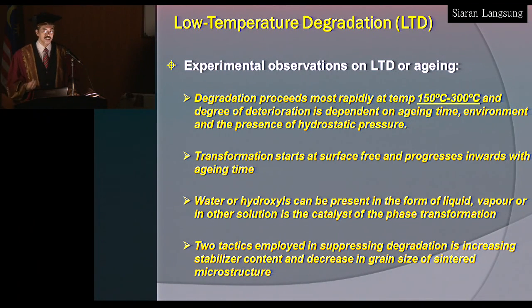Okay, but having water alone, it will not work. It has to have temperature. And it becomes worse when there's hydrostatic pressure. So two tactics employed in suppressing degradation are increasing the stabilizer content, that is the yttrium oxide content in the structure. But this has a bad effect because it overstabilizes the tetragonal structure into cubic form, and it loses transformation toughening. And the other strategy is to decrease the grain size of the sintered material.